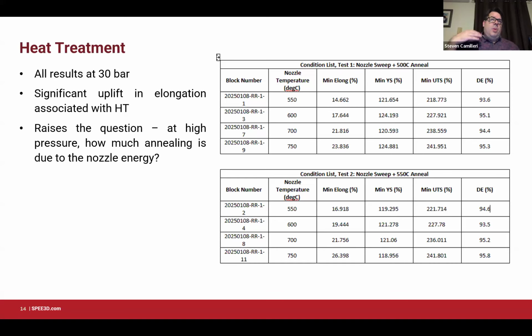So really, one question that's always been in our minds is, as we're cold spraying, we know that we're adding heat to the part. We know that that's causing oxidation. But if we do see annealing behavior at low temperature, is that of benefit? We're effectively doing some heat treatment with the nozzle as we spray.